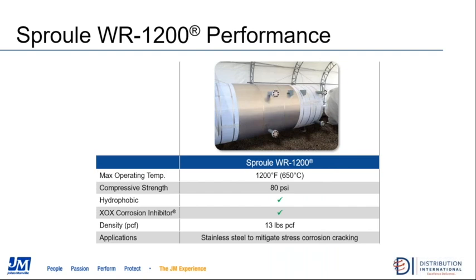The summary, I've talked about most of this already. Historically, it's been installed through the years on stainless steel piping because it's always performed very well with stress corrosion cracking, mainly due to the fact that it has a corrosion inhibitor in it and it's hydrophobic, so it's always performed well there, although now it's specified extensively also on carbon steel pipes.